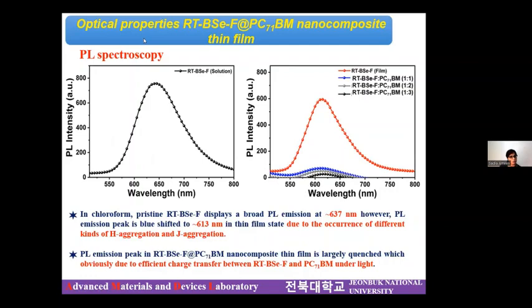Then we performed the PL spectroscopy, and this is the PL spectroscopy for the solution. We found a prominent peak at roughly about 637 nanometer, and this peak is due to the occurrence of certain interactions, whereas when we measured the film, we again noticed a shifting, which might be due to the occurrence of certain kinds of aggregations, say the H or J aggregations.